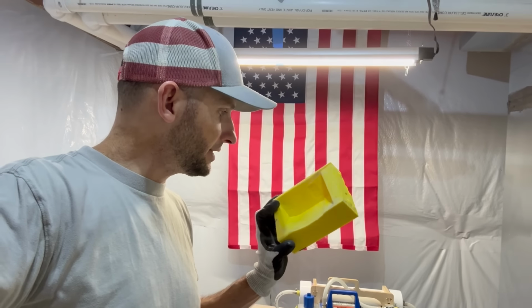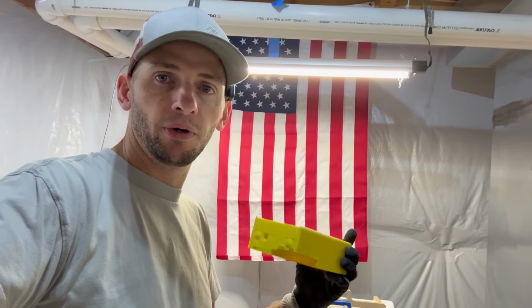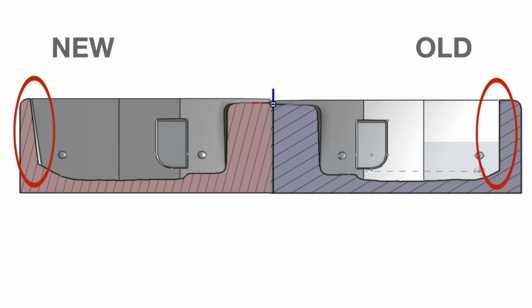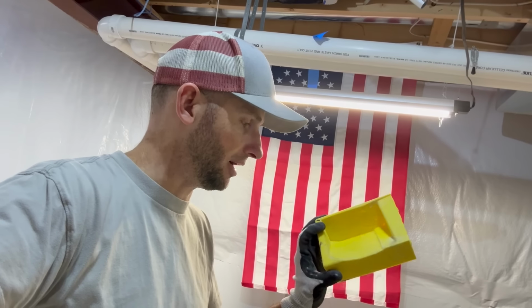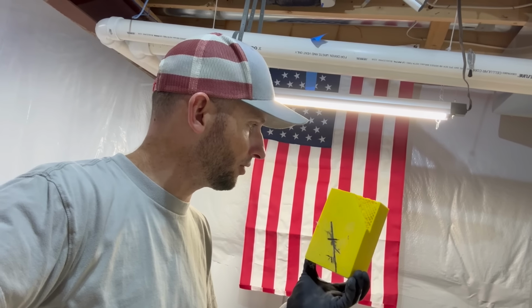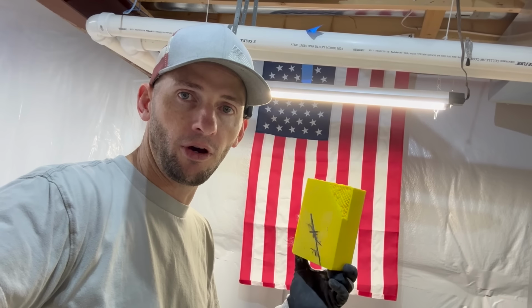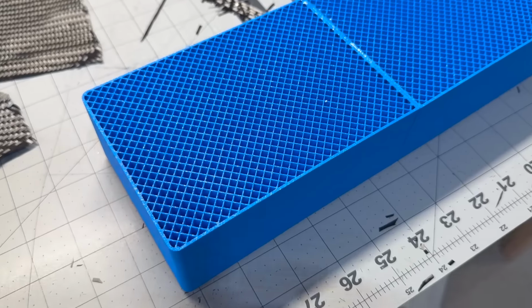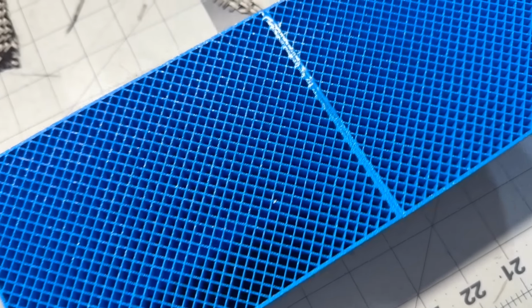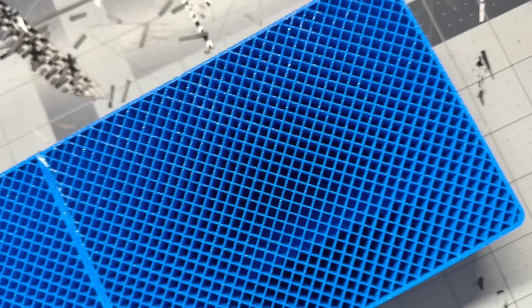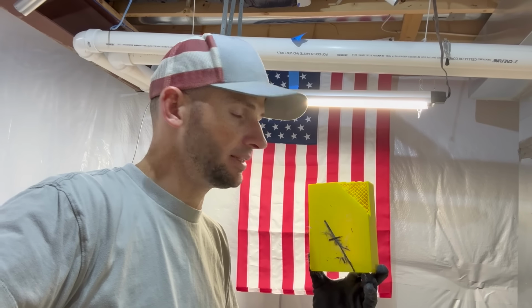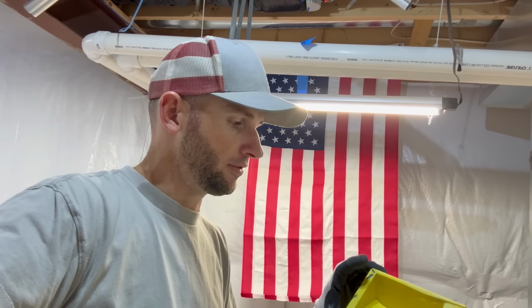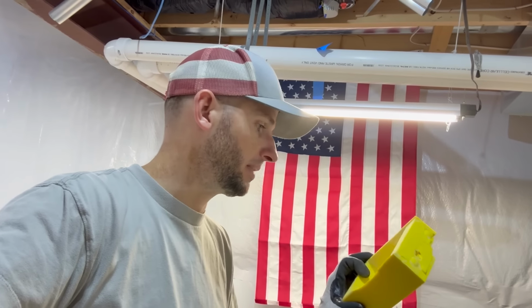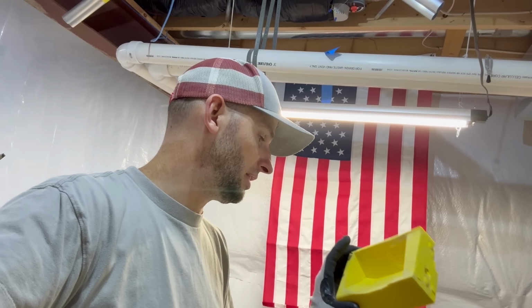So I'm going to redesign the mold. I'm going to put a better draft angle in here because there's no reason for it to be vertical. That should help the part come out. I'm also going to print this thing with no layers on the base, so the vacuum has direct access to the infill, and that should prevent any of that trapped air from going through the surface and into the part, and it should just come straight out the bottom. So I think that's going to help.